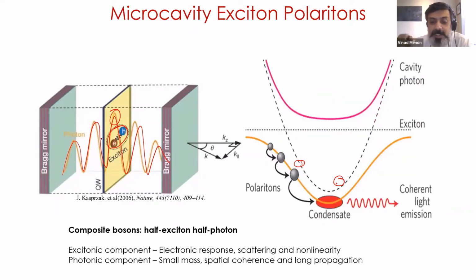So the early interest in all of this was because people were interested in condensation of these things because they behave very similar to atomic condensates, or at least that was a prediction. So the idea here is that you excite polaritons, they scatter, and if you get enough density of polaritons at the minima of your polariton branch, or at k equal to 0, then what you create is a macroscopic coherent state whose emission is coherent, but you have not created a population inversion in this system. So this was very fascinating. So you have a laser, or a coherent source of radiation, where you don't need population inversion.